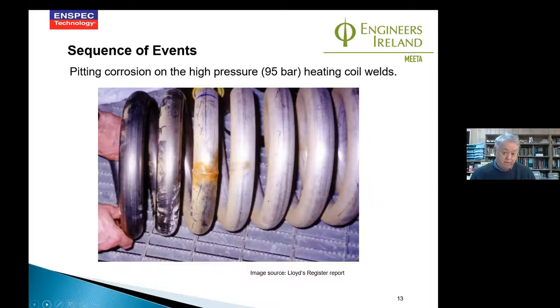When we see this kind of corrosion on stainless steel welds — any type of austenitic stainless steel — it tends to indicate preferential corrosion of the weld, and the usual suspect is chlorides. We had so many issues: how to repair the coils, who could repair them, who would pay for it, and how to physically take new coils through the manways, which were too small. As things unfolded, we reached a point where we had to think about the condition of the rest of the plant.